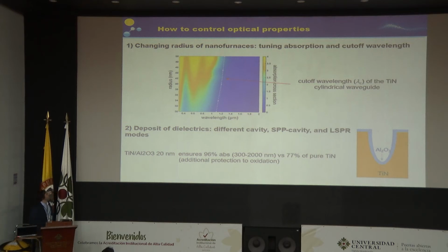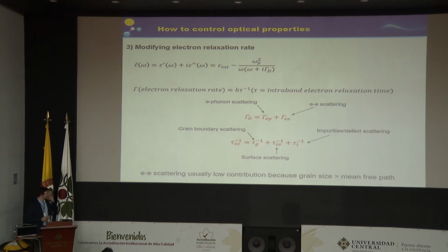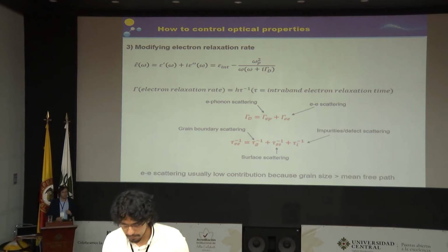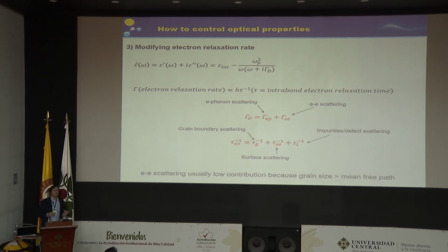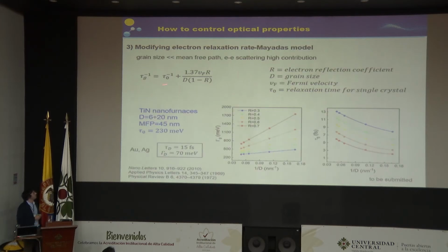Here, maybe I can skip this. But a fundamental and interesting property of these materials is that they are made of very small crystals of around 5 nanometers, which is quite unusual for plasmonic materials. Usually single crystal or e-beam lithography made materials are used, which have crystal sizes of 40 or 50 nanometers. When you have such small crystals, the dissipation or the electron relaxation rate can be really influenced by electron scattering at grain boundaries. So we used a very simple model, Mayadas model, which connects the size of our crystals with the electron relaxation rate, or the electron relaxation time.